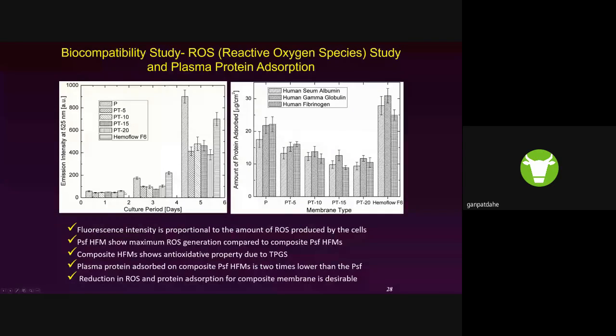As time increases, it's obvious that the ROS, reactive oxygen species content, increases with time. But compared to the first one, which is the pure polysulfone, and the last bar, which is the commercial membrane, this composite membrane shows lesser reactive oxygen species generation.